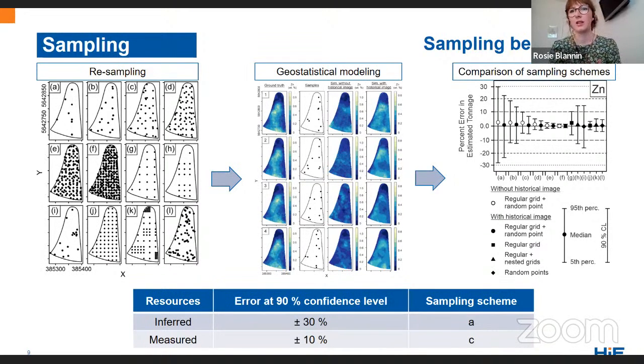At a certain point, there's not much benefit of taking more samples. So maybe after scheme C, which I think is around 30 points or something like this, then probably it would not be necessary to take more samples. We can also see when we compare the black points to the white points that when we use the historical image, the error is typically decreased.